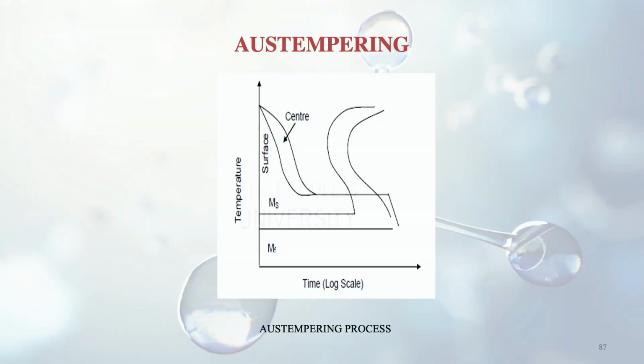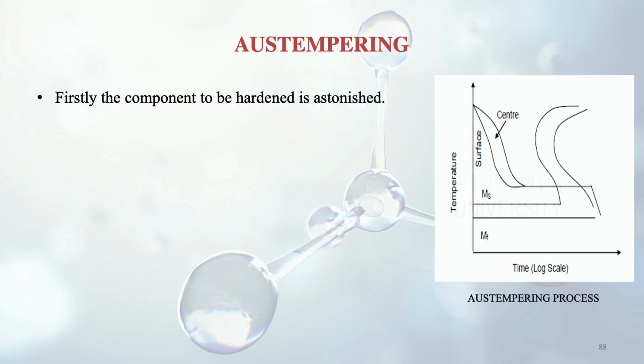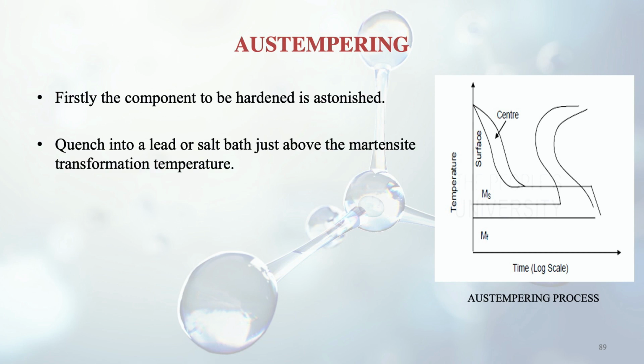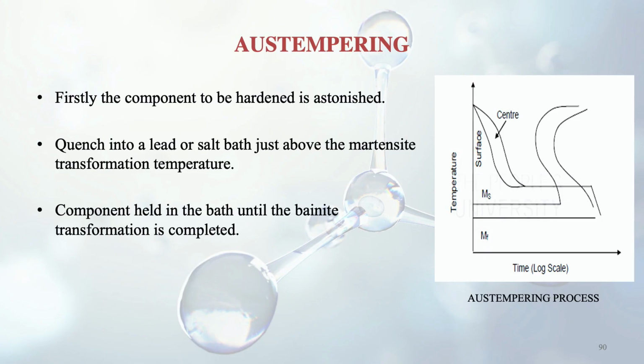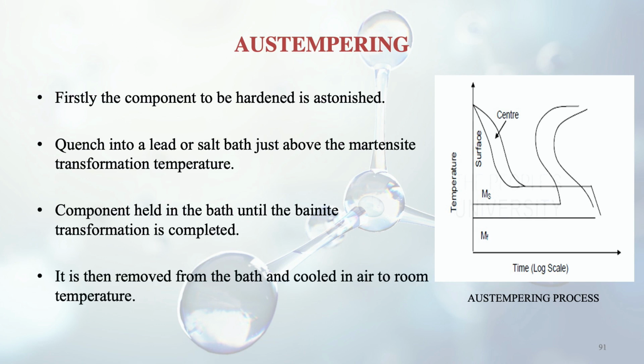Further we move on and discuss a new special treatment, that is austempering. What is done in austempering? If you see this TTT diagram, where time is on the log scale and temperature is on the y-axis, first the component is austenitized, like earlier also we have seen. Austenitizing takes place in austempering also, and then it is quenched in a lead or salt bath just above the martensite transformation temperature. So this quenching is done up to a temperature just above the martensite transformation start temperature. The component is then held in the bath until the bainite transformation is completed, and then it is removed from the bath and cooled in air to room temperature.